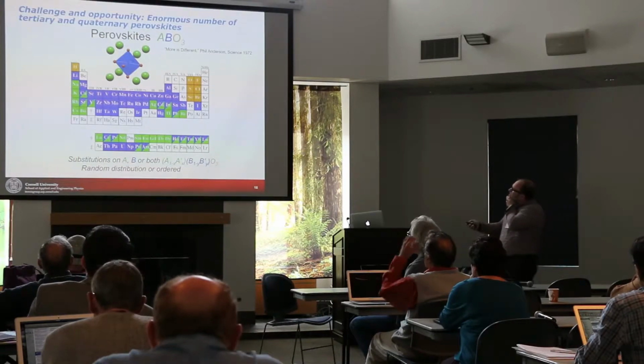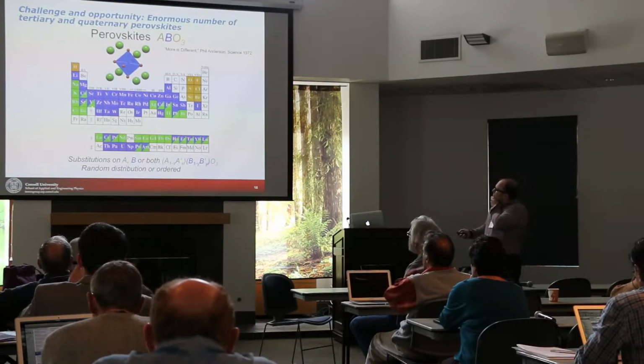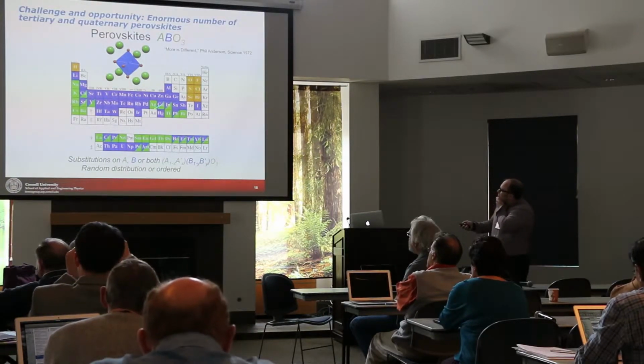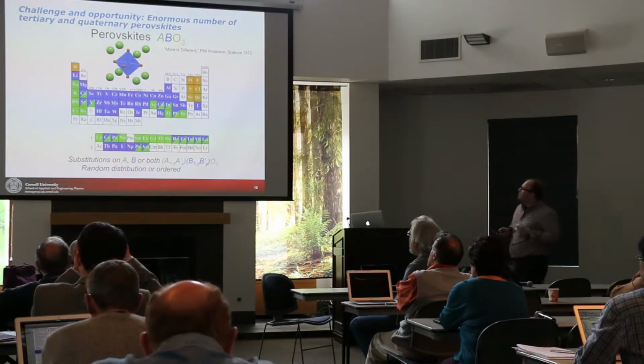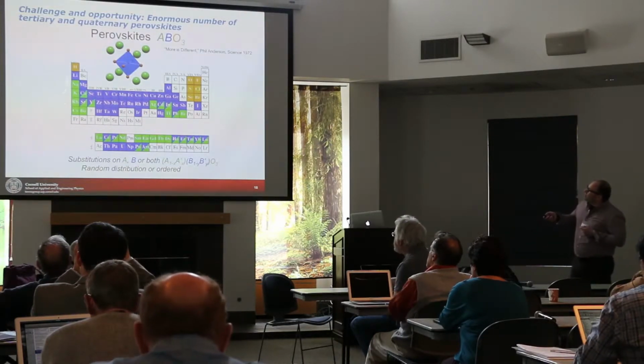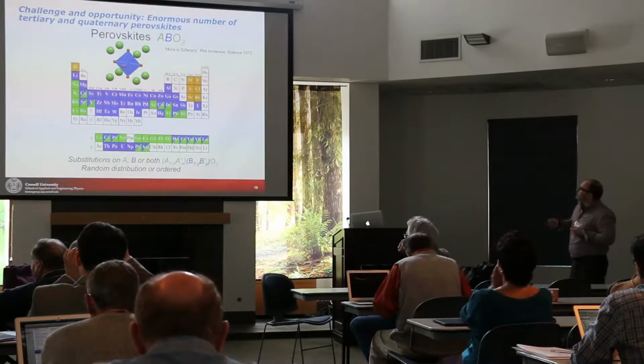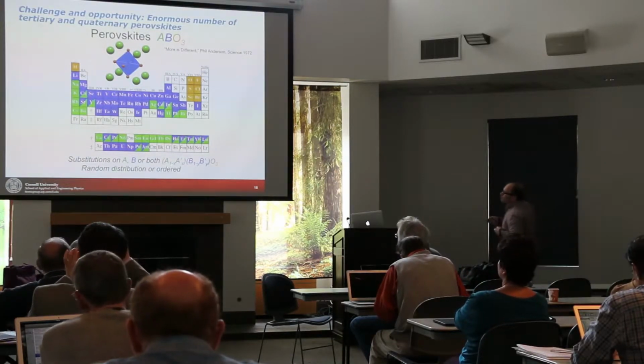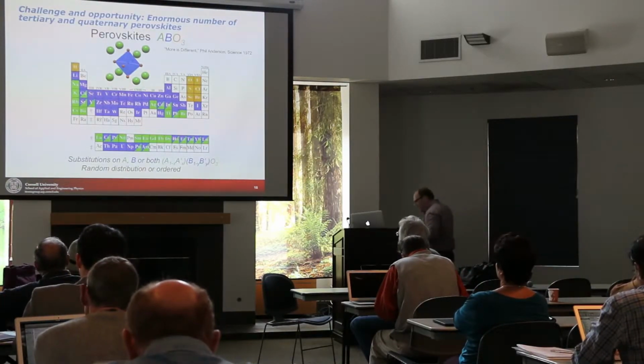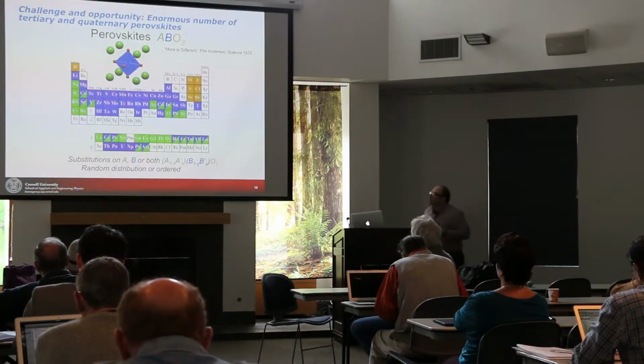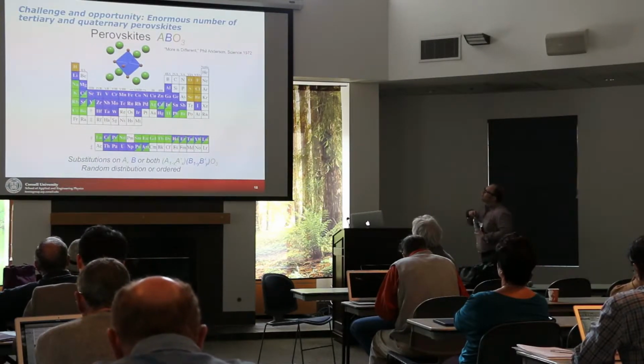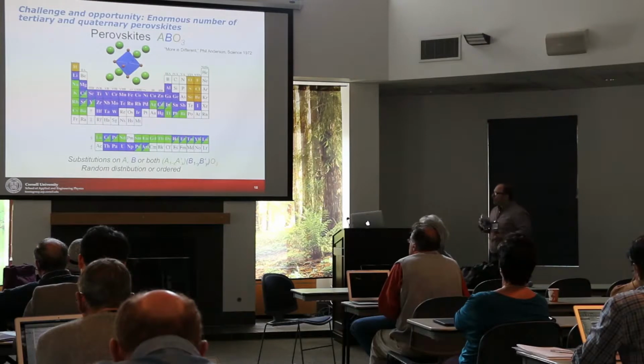into the structure. So these color codes are supposed to suggest that just all the transition metals, these blue things here, can fit on the B site. All of the alkali metals, all the alkaline earths, the lanthanides, they all fit on the A site. You can have multiple cations on the A site, multiple cations on the B site. You have an enormous number of possible compounds that can exist in just one structure.